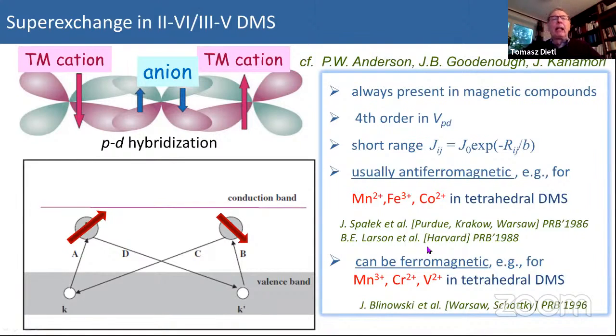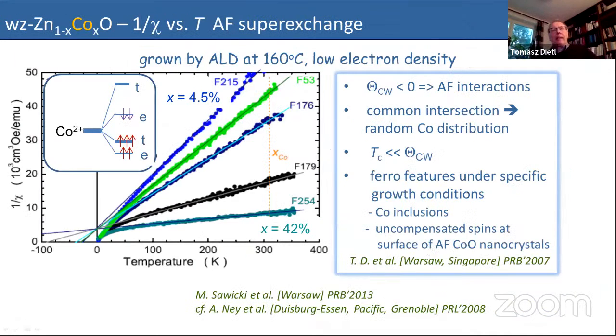And let's start from this antiferromagnetic interaction as an example. Of course, there are plenty in the literature. What we study here is zinc cobalt oxide, a material which many people have been studying. Many groups were interested in this material for various reasons. And what you see here is inverse susceptibility plotted as a function of temperature. And you see immediately that the interaction must be antiferromagnetic because the Curie-Weiss temperature is negative. And you see that a common intersection of these curves occurs.